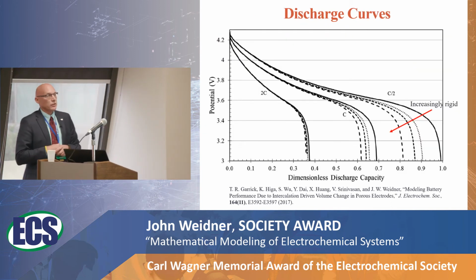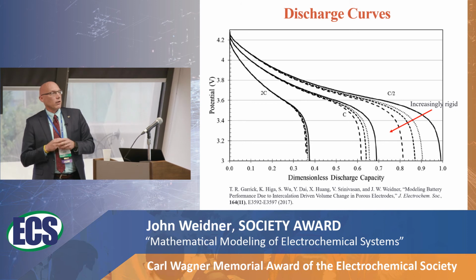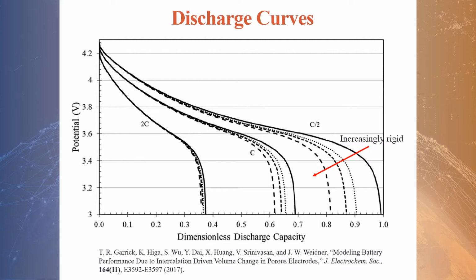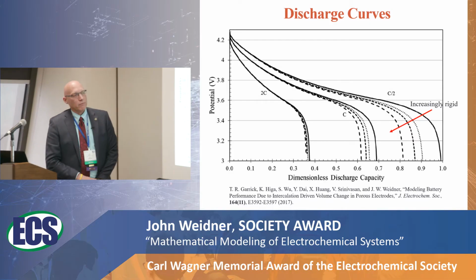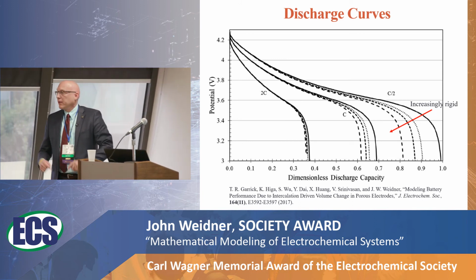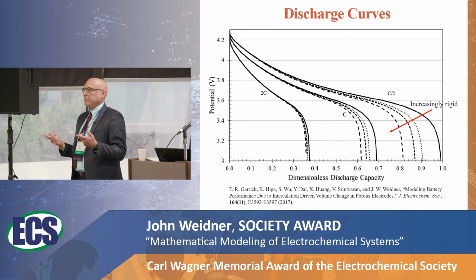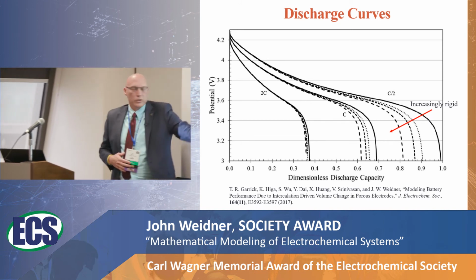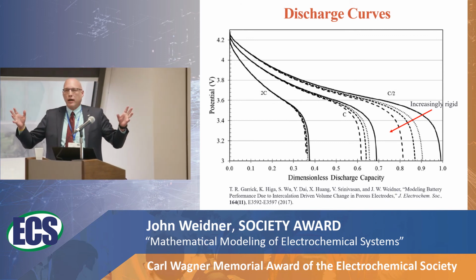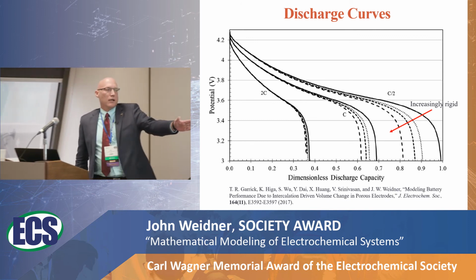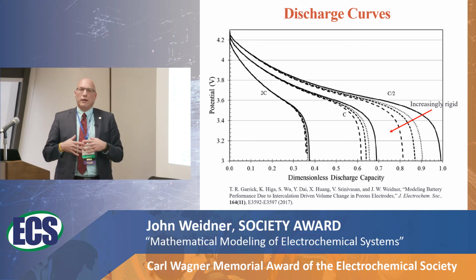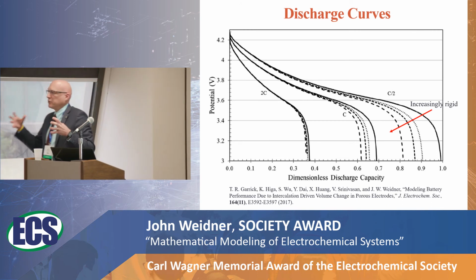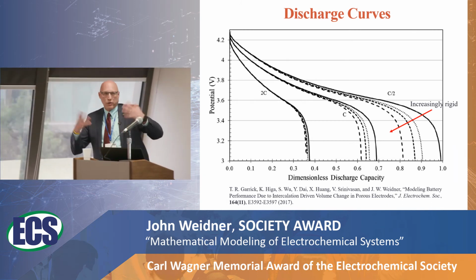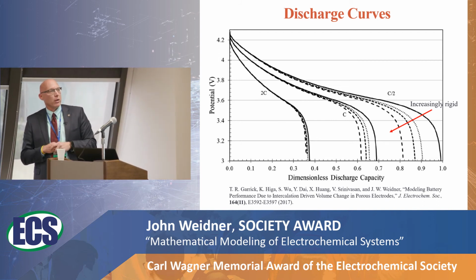So here are some discharge curves from the lithium-ion battery model from LBL. We see kind of the same thing we saw before, in that the more rigid it becomes, the less capacity you're going to get out of the cell. However, now we can understand a little more that it is rate dependent. If you do it at very high rates, you don't see much effect. That's because most of the capacity has been withdrawn before you had a chance for these pressures to build up inside the cell, before the rigidity can actually play a role in the process.